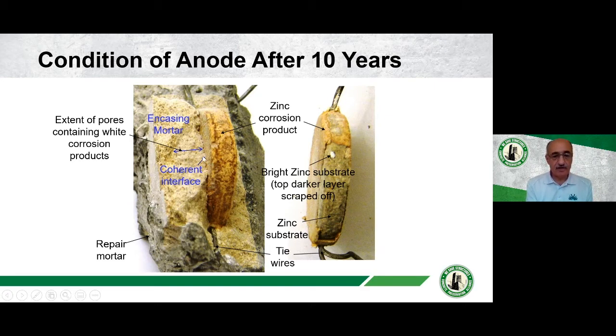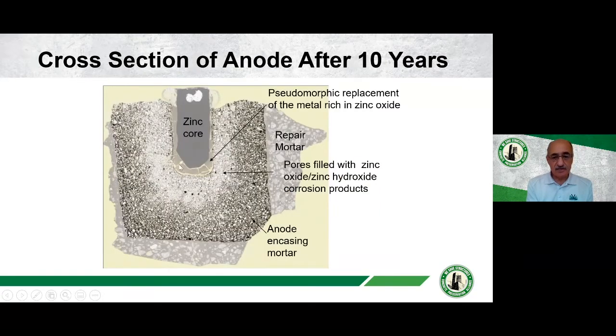There was no cracking or anything, but we could see a lighter face down here, which when we looked at closely, we could see as a cross section here under a special light. This area was actually filled up, or the pores were filled up with corrosion products, zinc oxide corrosion product. So it now looks quite clear really how the process was happening. The zinc was corroding. The empty space that was left behind was filled with the corrosion products, and the remainder of the corrosion products migrated into the mortar, which was porous.